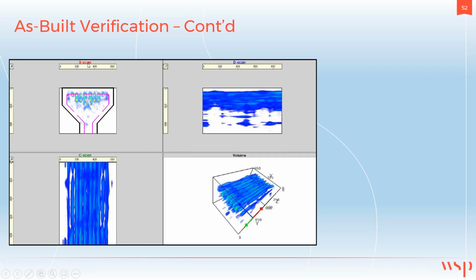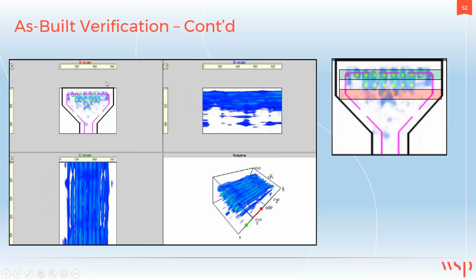When you look at the B scan, which is the girder's cross section, we can identify at least 3 distinct layers of tendons. But for more details, we need to look at specific cross sections. As I move to a different depth, please pay attention to the C scan and volume views down here.